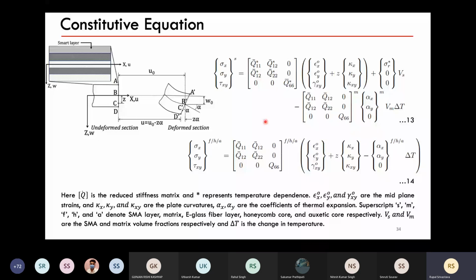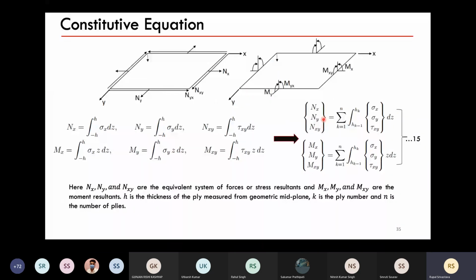And for the other layer, if it's a fiber layer, a honeycomb layer or an auxetic layer, this is our equation, which is a very simple equation with our midplane strain and curvature, and then our alpha delta T. Okay, I solved these equations using FEM, and this is how I calculated and got ABD matrices. Just remember that in plates, when we calculate our stress resultants and moment resultants, we always calculate them at the midplane. If you cannot take everything from the talk, just take this: when you are talking about composites, they have multiple layers and different materials stacked on top of one another. We always take the material properties and the stress resultants and the moment resultants at the midplane, the geometric midplane.